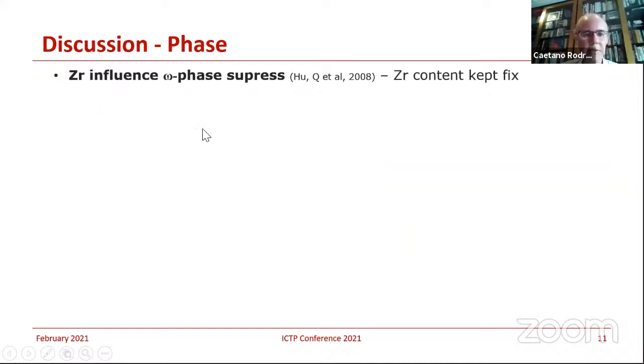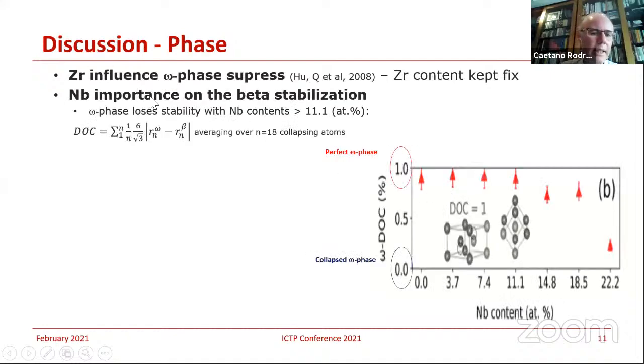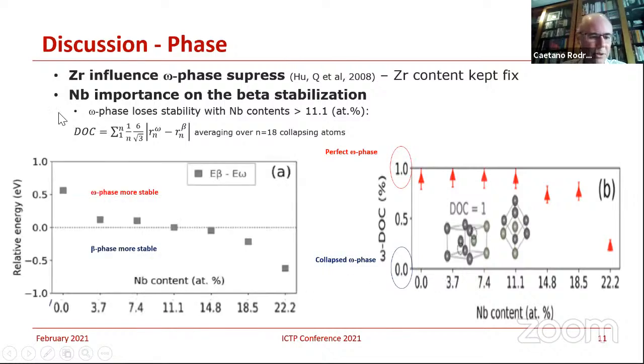So you look for the influence of the zirconium, then you keep this content fixed. Then you change the amount of niobium, because the niobium stabilizes the beta phase in titanium. So looking for this degree of collapse between the omega and the beta phase, where you have the perfect omega phase, and here will be the beta phase, and also the competition in energy between those. You could see that if you change the amount of niobium in the system, then at regions above 11%, you stabilize this beta phase. That is the one that you would like to go.